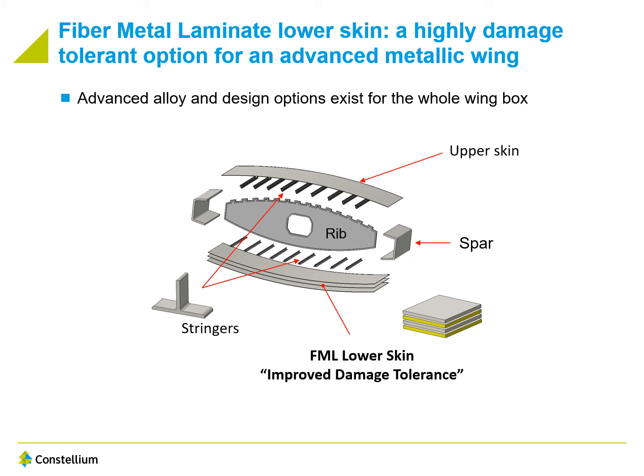Fiber metal laminate is a proposition that we make to have a very high damage tolerance lower wing, associated with an improvement of the overall wing concept with advanced alloys of the aluminum copper lithium family, Airware family, and associated with bonding and also friction stir welding. Fiber metal laminate skin is a way to have a robust weight saving, whatever the assumptions regarding the inspection intervals or the design service goal, more or less.